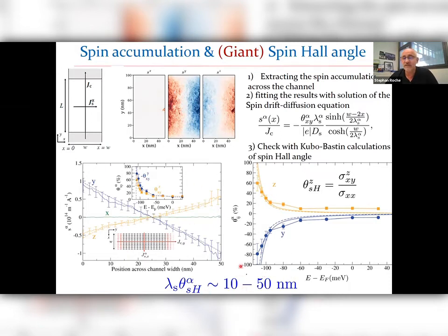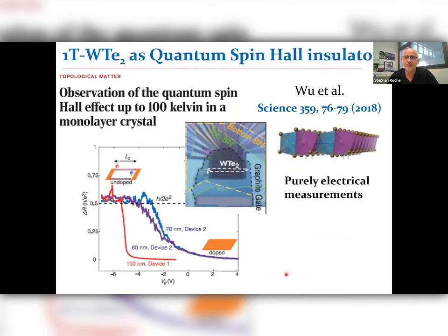And as a result, the most important figure of merit that we found for this type of materials is of the order between 10 and 50 nanometers. So indeed, for these materials we don't reach 300 nanometers as the extraction from one paper was claiming, but definitely we are going to orders of magnitude that are extremely high, and so this shows that this new type of materials could present a high value in the context of spin transport devices.